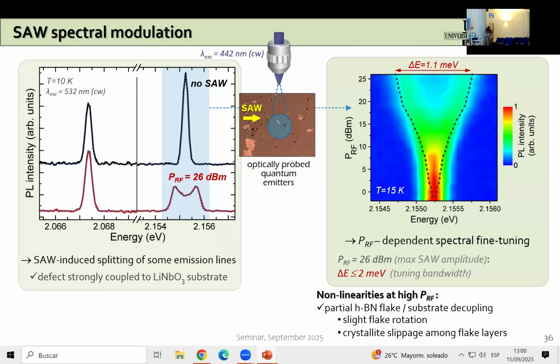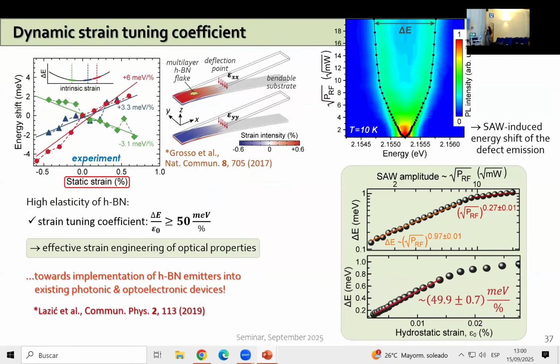So what we actually need is a defect strongly coupled to the substrate in order to observe such behavior. For some future experiments, we plan to encapsulate these grains or HBN flakes into some transparent piezoelectric material so that we could improve the coupling and get single photon emission affected by the acoustic wave in all cases, which is important for practical applications, of course.